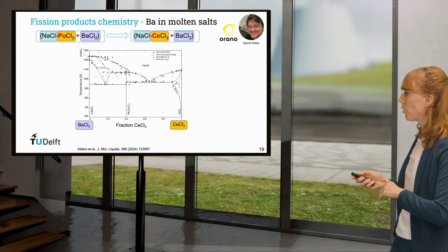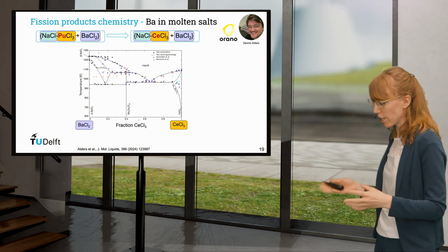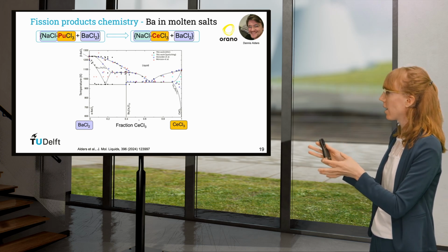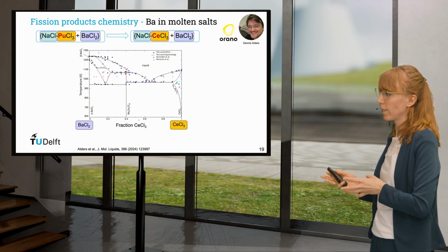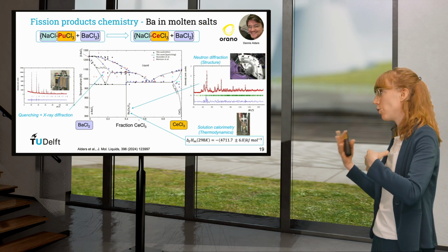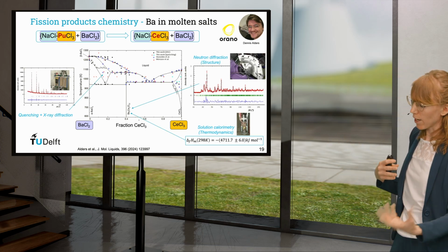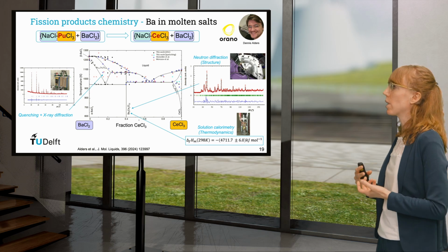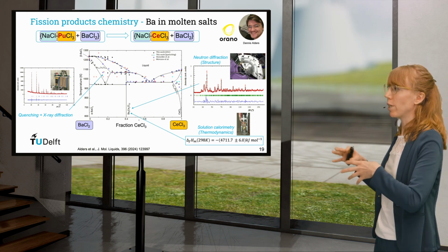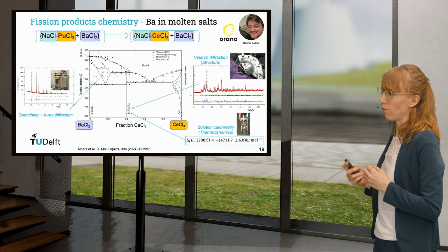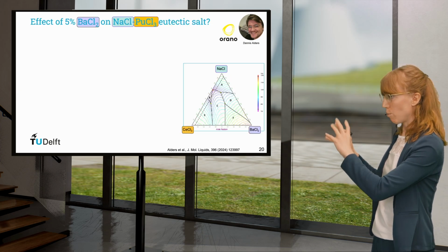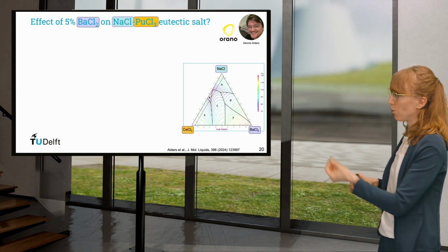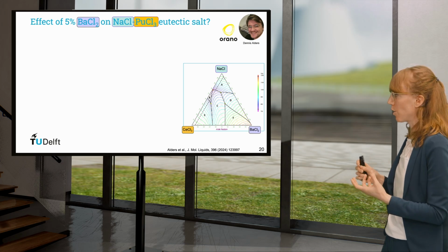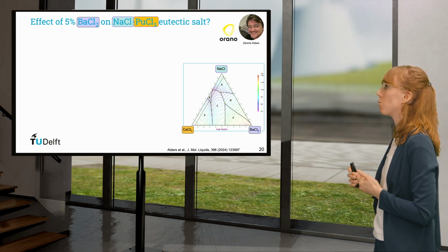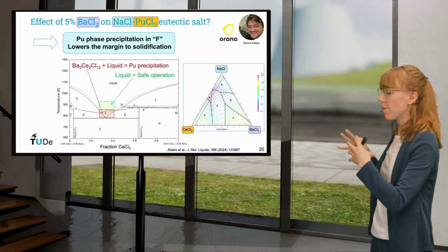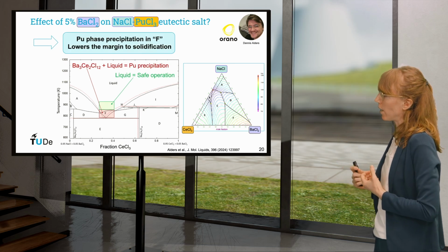We want to know the consequences for the fuel chemistry. So we did some fundamental studies, and I will not go into the detail. You just see that we have a complicated phase diagram, much more complicated than the one we saw before. So we need to do structure studies, calorimetric studies, quenching experiments. But in the end, we get a detailed picture, and we get a model of that system. We can then build a model with 3 elements, the sodium, the barium, and the cerium. Cerium, you remember, is a surrogate for plutonium. And with that, we can make, again, application calculations.